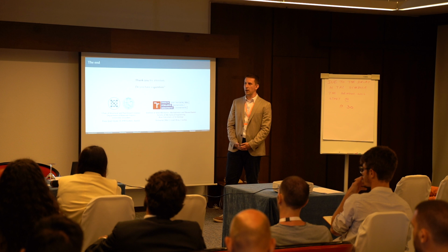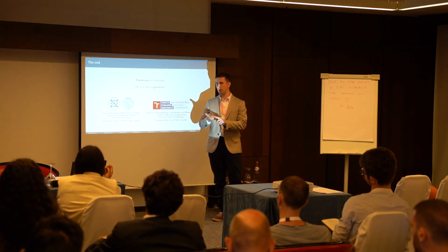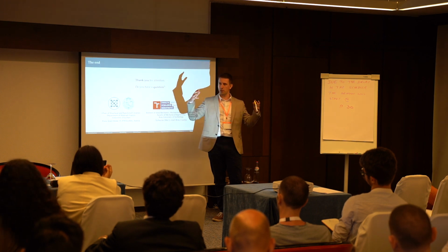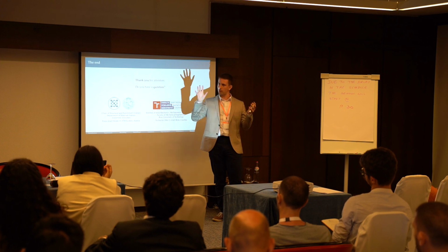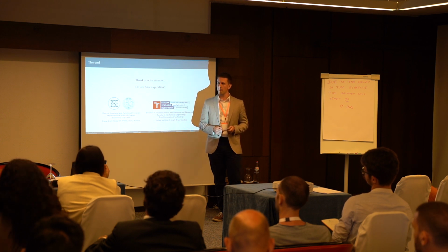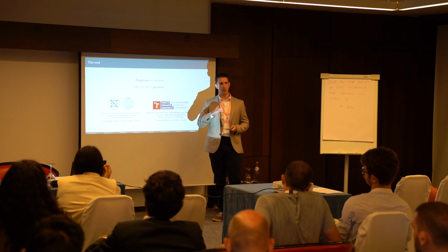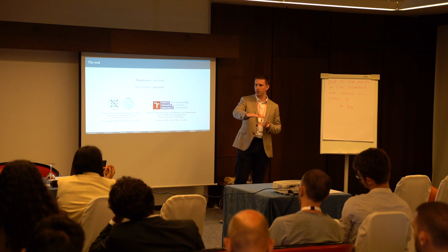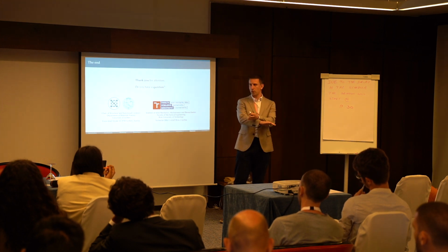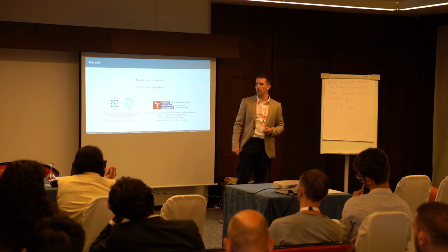If I know the data from the literature, for alumina, we have it. Silicon nitride, we have it. So I did not have to match the residual stresses to fit the data. I just took what is in the literature, and it was working. So you look in the literature for what residual stresses would be there, and then you apply that and it matches. There are experiments where people compare the residual stresses when you polish it, when you grind it, transverse direction, longitudinal direction. So data are there, and we can use this data to predict.